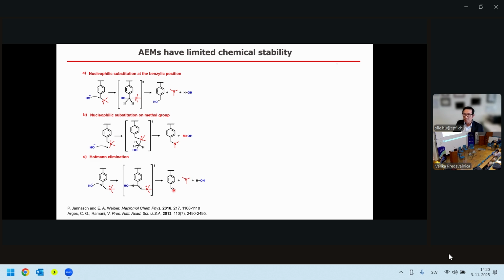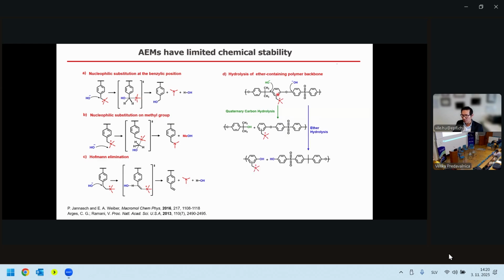But also the polymer backbone has a problem. And previously people like to use aryl ether ones, and these plastics are really easy to get. However, in fact, hydroxide can attack and do replacement. Hydroxide can also attack quaternary carbons and so on. And so you basically cleave your backbone, and then you don't have your polymer anymore. And so chemical stability is a challenge.